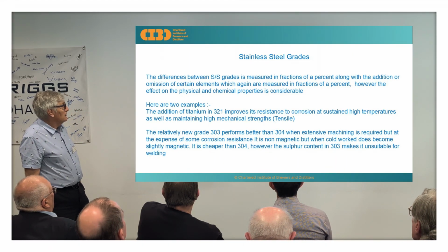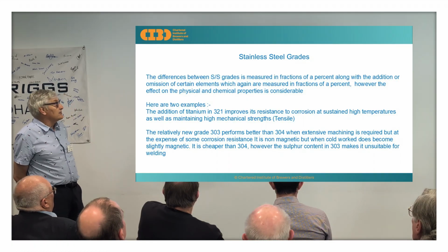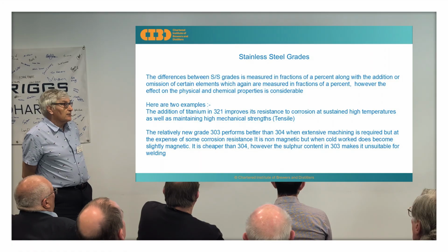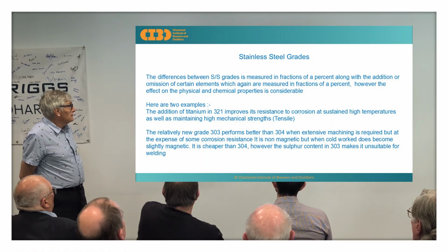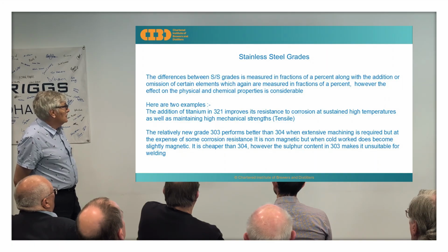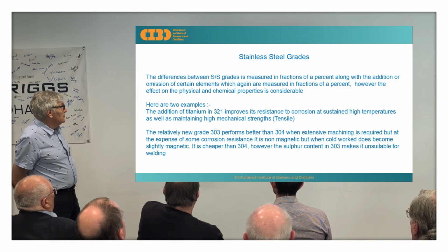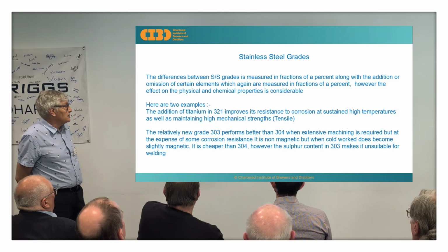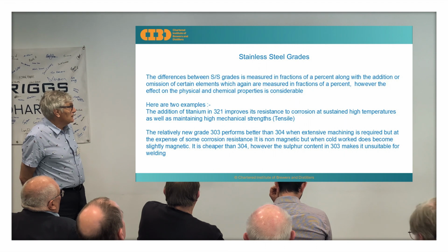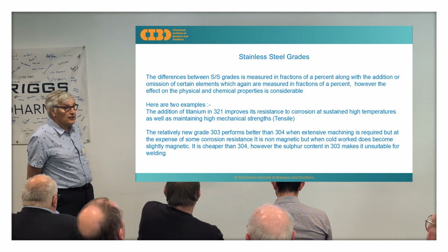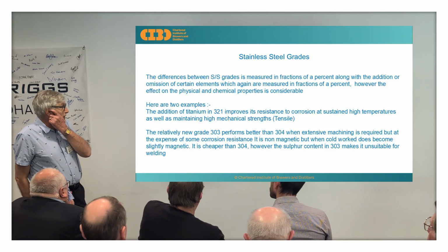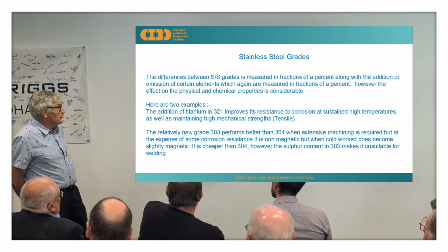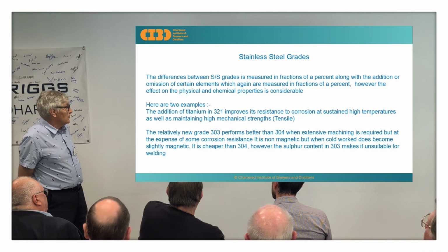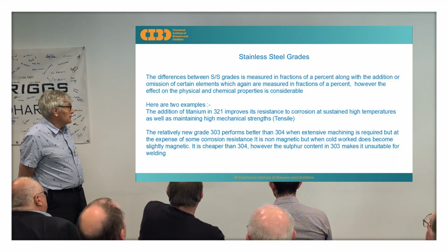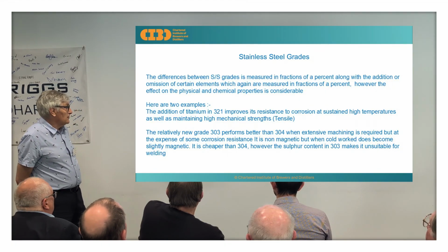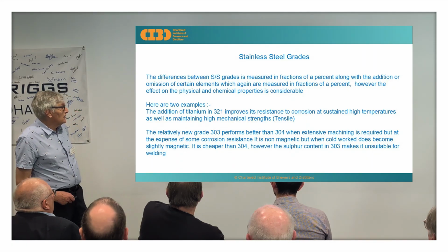So, the differences between the stainless steel grades are measured in fractions of a percent, along with the addition or the omission of the elements. There are two examples here. The addition of the titanium in the 321 ups its resistance to corrosion at sustained high temperatures, as well as maintaining its tensile strength. This relatively new grade 303 performs better than 304 when extensive machining is required, but at the expense of some corrosion resistance, and the sulfur content makes it unsuitable for welding.